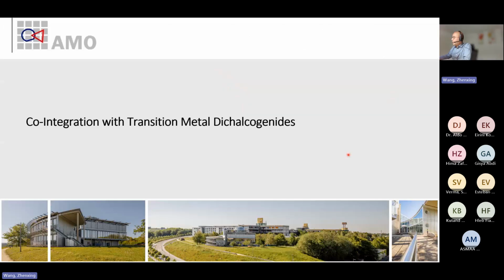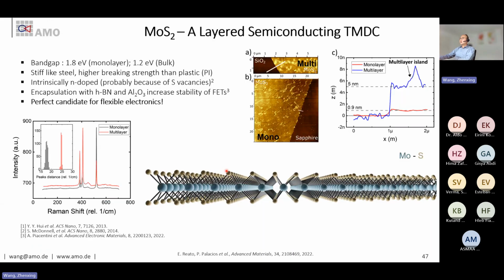Then I will talk a little bit about this co-integration of graphene with TMDs. As I already mentioned many times, MoS2 is another nice 2D material. Compared to graphene, it has the advantage that it has a band gap. For monolayer, it has a 1.8 eV band gap. For bulk, it has 1.2 eV. It's also very good for flexible electronics.